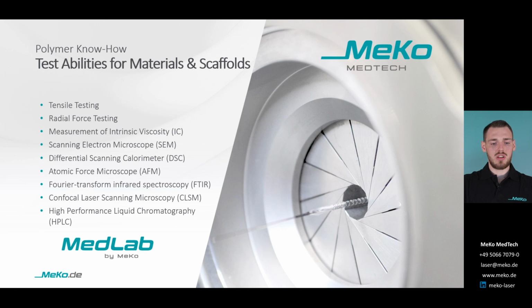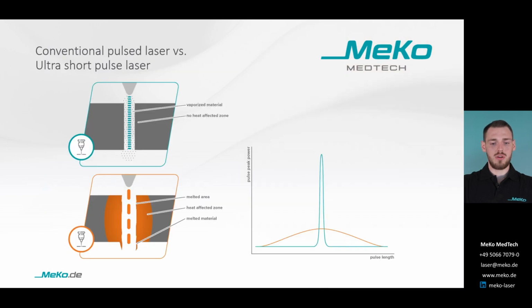Now let's take a deeper look into the laser technology used for BRS manufacturing. The figure below on the left represents a conventional pulse laser technique. Here the laser generates a melt bath, which is then blown out by a directed high-pressure gas beam. This is also a great technique used for highest precision manufacturing, but due to the heat which is introduced to the material, it is not suitable for polymer processing. Instead, for the polymers, you need to use an ultra-short pulse laser system.